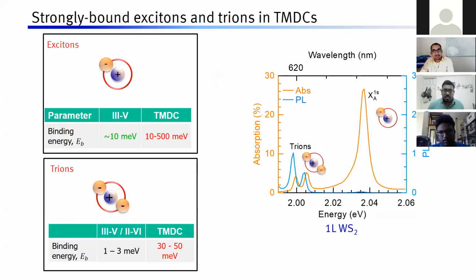Yeah, this one. So why can we see an exciton PL peak here? Oh, so there is this exciton PL peak. It's a very small peak. First of all, this is a dark material. This is tungsten disulfide, and this is a low temperature spectrum. So then most of the PL is coming from low energy trions, and in fact, lots of PL is quenched because there are dark trions and dark excitons as well. The dark excitons also appear somewhere in this energy region, which I have not shown.